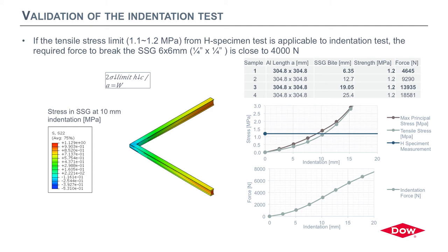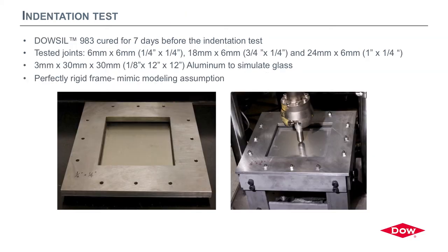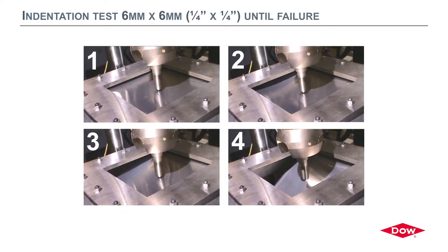We prepared samples with three aspect ratios: 6×6, 18×6, and 24×6 — corresponding to aspect ratios of 1, 3, and 4. The aluminium plate is bonded to a perfectly rigid steel frame, as described before.